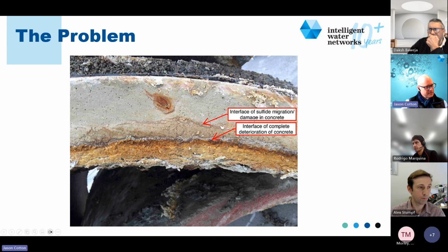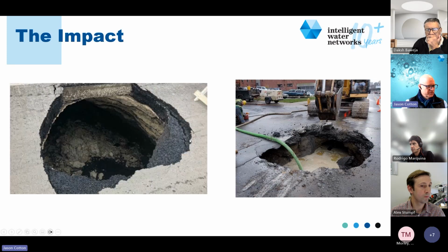So you can see here that as you get this porous degradation and that falls away, you then get the second layer where it starts to degrade because the sulfide migration is occurring in that concrete. And that is not a good thing, because what that leads to is sewer collapse. Now, you can imagine the network of sewer that's underground. And if you start getting collapses of sewers under roads, under runways in airports, under houses, that's a massive issue. And so we want to solve for this problem.